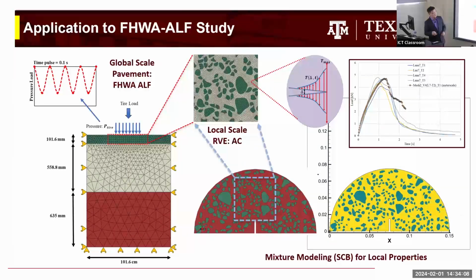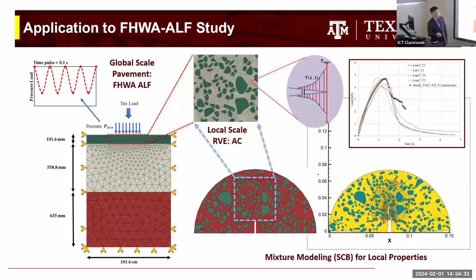Here is an application again, to the Federal Highway ALF study. We tested just upscaling, one-way coupling. Here is a snapshot of the entire figure, from the mixture, let's say SCB, and we can find the SCB fracture properties from this level of effort. That will be input for the two-way coupled multiscale scenario, where I get a representative volume element directly from your SCB sample and link it to a structure with this amount of global elements. Here is the global scale, and this is the local scale, including any crack development, if you wish.